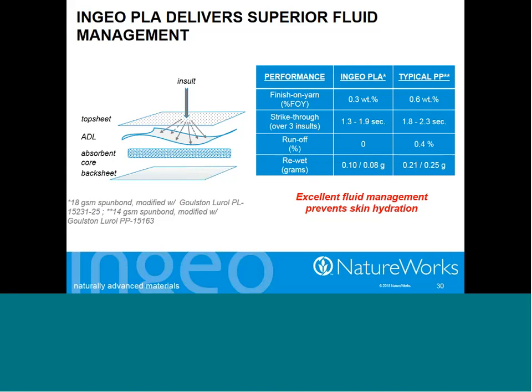In that test, it's the amount of water that makes it across an angled piece of fabric without soaking in. So we pass that test with no material reaching the edge of the fabric. And then re-wet is the measure of the ability of the water to pass back through that top sheet if the SAP layer is compressed. And so what you would like to see there is, again, a very low number, and in fact we do better than polypropylene in all three of these cases. So all of this leads to better skin care and less skin irritation.